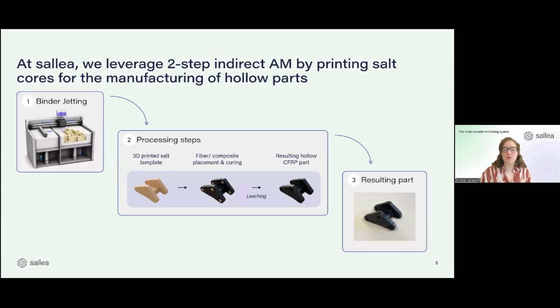So I want to focus a bit and explain in a bit more detail how we leverage that. So we also use this two-step indirect AM method to structure materials. And we do that only for materials that are either not directly printable, or that can be printed, but not at the resolution needed, or not with the mechanical properties that it needs for the end use. And we do this by using binder jetting as a 3D printing technology.